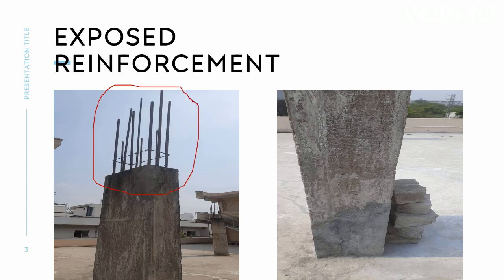The construction was made around 2006 or 7, and the steel in the column was left out for preparing the next slab, but they did not continue. So within 14-15 years, the steel has corroded fully. Because of this corrosion, the reinforcement has expanded, and cracks have appeared everywhere.